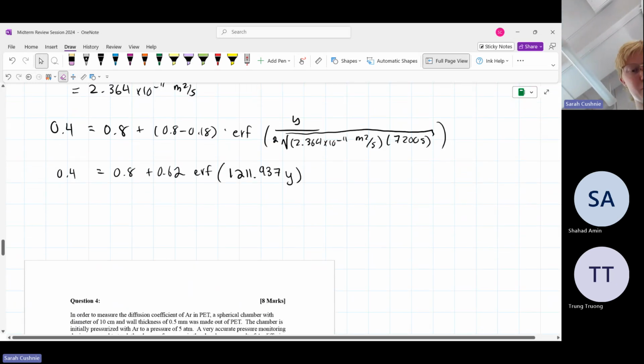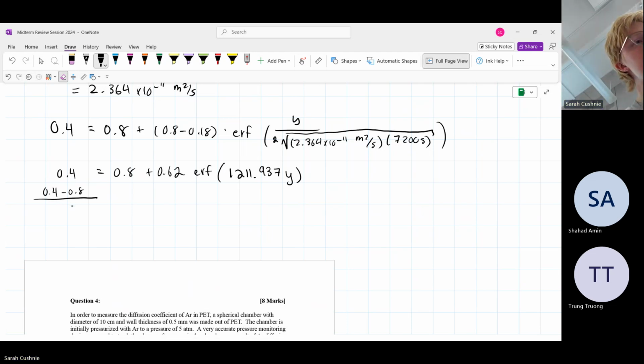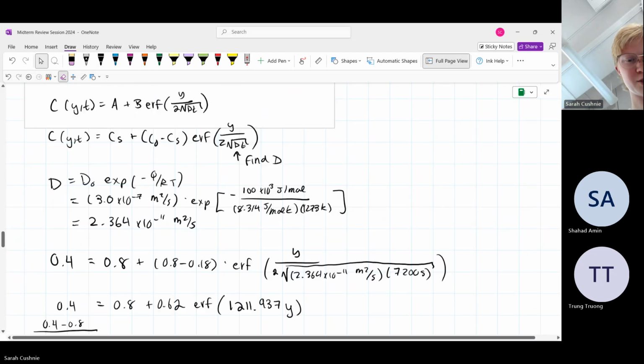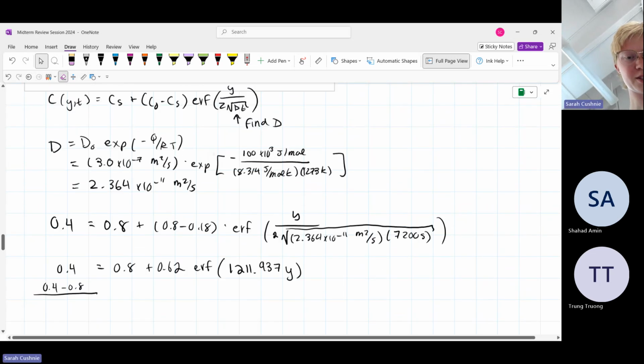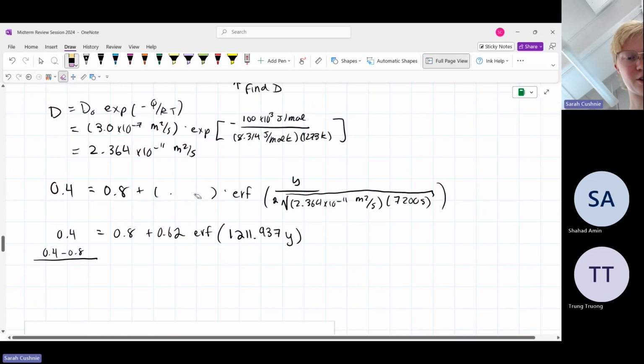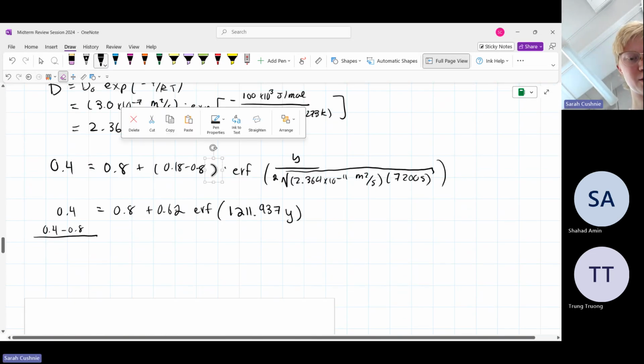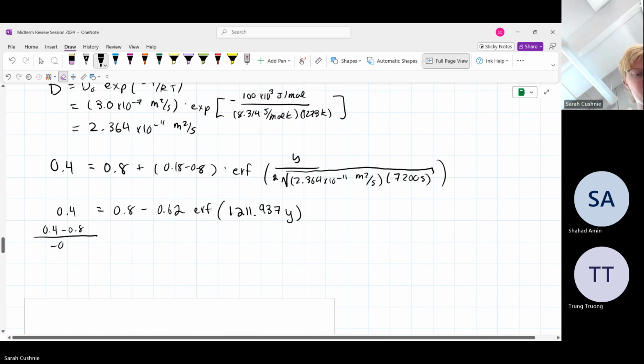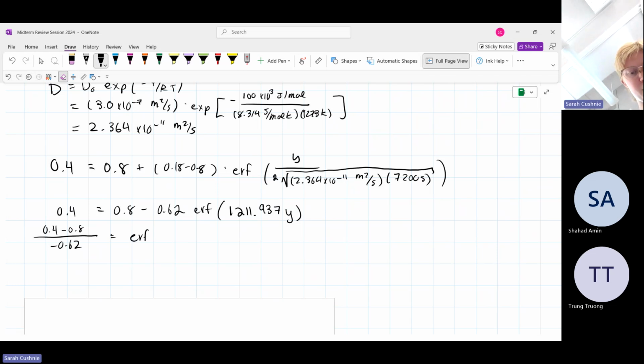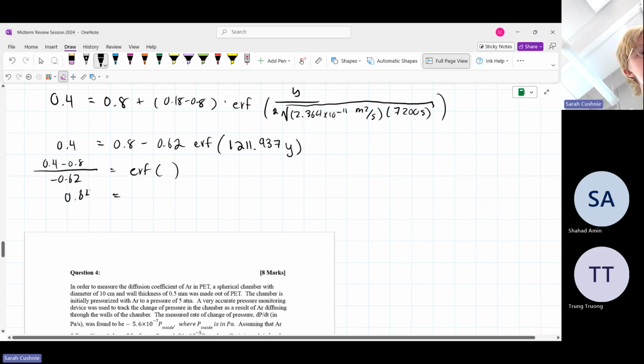So now we're just going to rearrange and put 0.4 minus 0.8 divided by, oh, because I swapped these around. Okay, so it's C naught minus CS, so 0.18 minus 0.8, which is minus 0.62, is equal to the error function of whatever it was. So now we're going to end up with the value of 0.6452 is equal to the error function of 1211.937y.